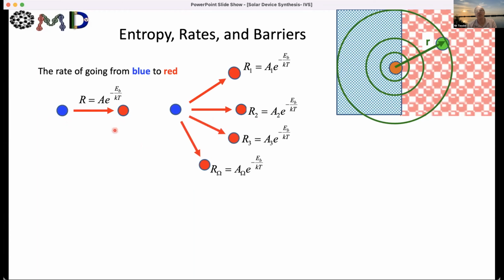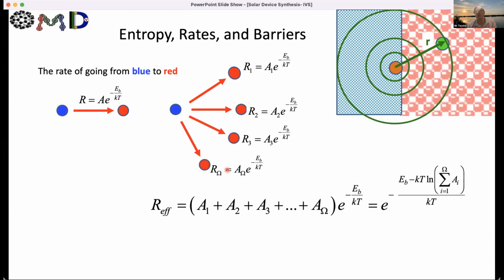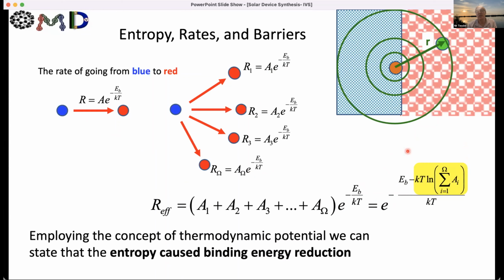So really if we had only one rate, now we have loads of different possibilities. And if we sum them up, we can come up with an effective rate that has the binding energy minus the sum of the contributions, because we have many options. And this is really what we call entropy. This is really hand waving just for this case. And all this is known when we know that the binding energy is effectively reduced.